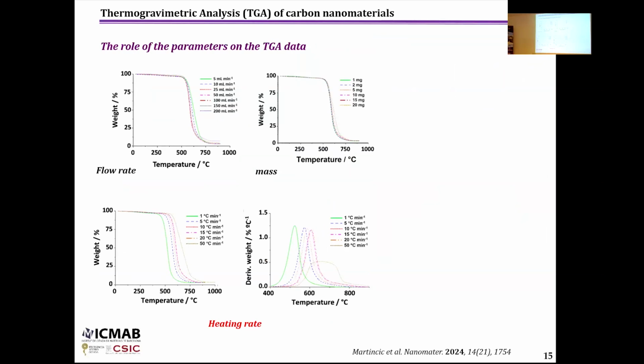One important thing about the determination of the thermal properties of these materials is making a proper characterization. Usually thermogravimetric analysis is used for this characterization, but what we observe is that sometimes there is no concrete guideline in the conditions we use for determining this thermal stability. So we started to study how the parameters employed for TGA can have an influence on the results we obtain, because finally this is an orientation of the properties of the materials.